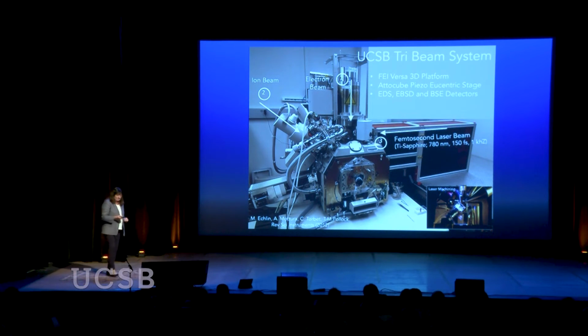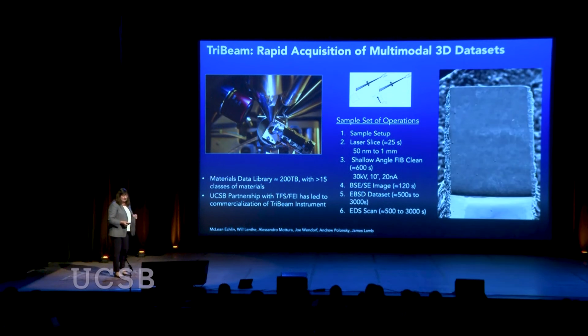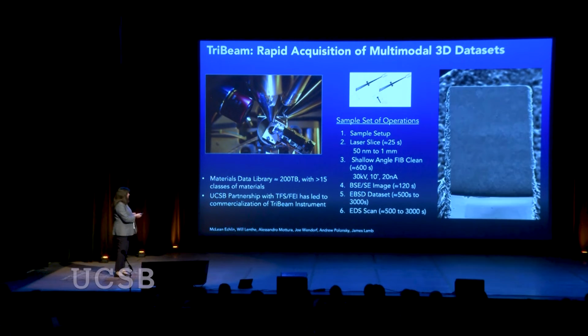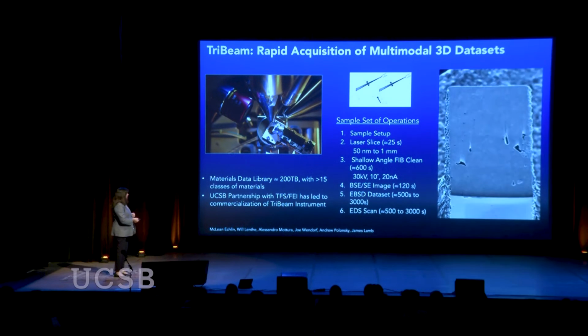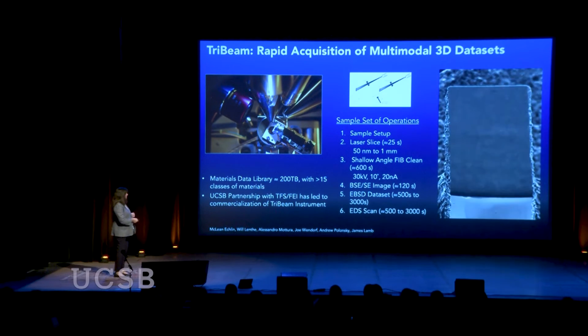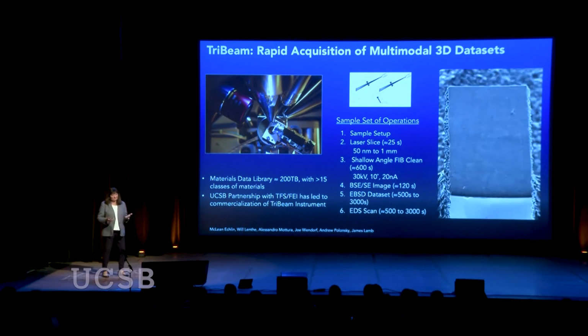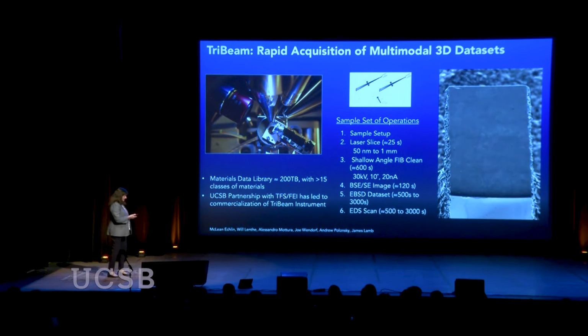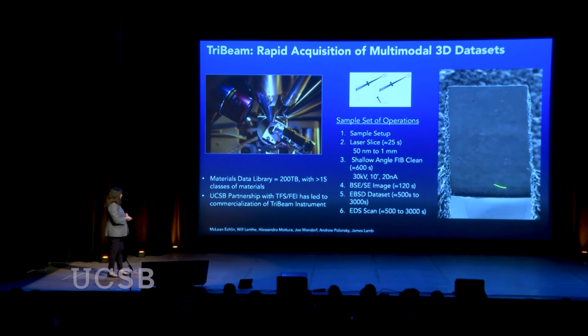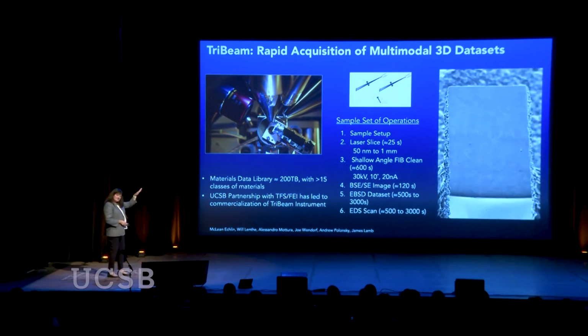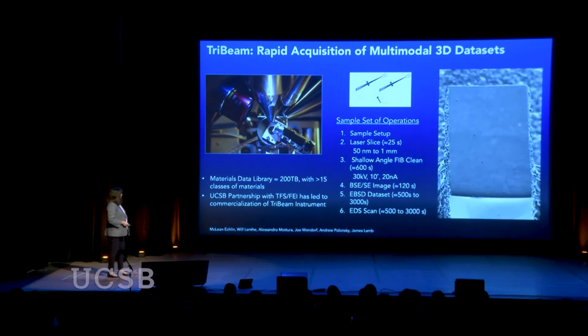Now, the role of the femtosecond laser is to serve as basically a nanometer scale knife. It will ablate a layer of material without doing damage and then allow us to get structural information. And so you can see the layers being removed in this movie. This is an additively manufactured alloy that usually we expect most additively manufactured alloys to have a lot of defects, and indeed this one does. And you can see them as we slice through the material.